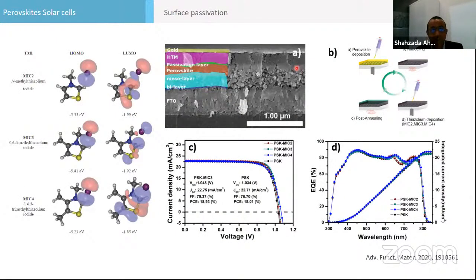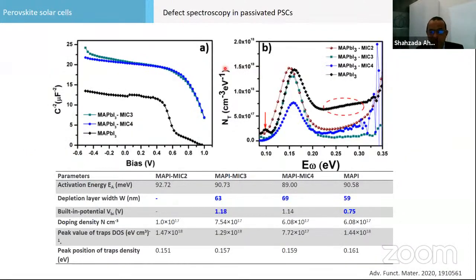This is one example. We did a passivation approach, which is very well established in silicon solar cells, and this was published last year. We used a thiazolium iodide compound, and we achieved efficiency a little bit improved, but the voltage was increased by 60-70 millivolts. A very thin layer we use as a passivation to just passivate the defects, and this shows a higher voltage. We studied with the help of defect spectroscopy more electrical parameters, and you can see the built-in potential was increased from 750 millivolts to 1180 millivolts. And why? Because the depletion length has increased, so carriers will travel fast.